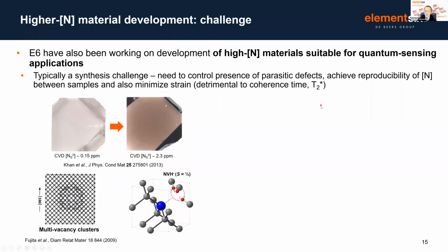So if we think about parasitic defects, it's most easy to introduce by illustrating what typically happens when you increase the amount of nitrogen in a CVD diamond sample. And this is what I show here. Instead of having a nice colorless diamond sample, what typically happens is the diamond becomes brown as we start to increase the amount of nitrogen present in this material. So this isn't because of the incorporation of nitrogen itself, it's by the presence of other, in some cases, nitrogen-related defects, such as the nitrogen-vacancy-hydrogen center in this material, and also things like vacancy clusters that can form. It's a combination of these two things that erodes the optical properties of the material.